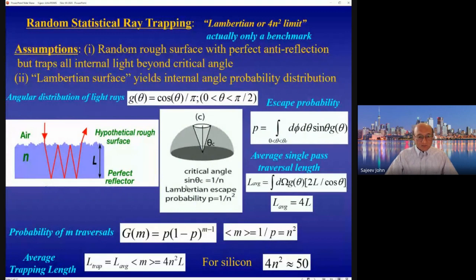So you could ask, what is the probability that light that enters the structure by this Lambertian rough surface would end up escaping from the structure? Well, if you have a material with a refractive index of n, you know from high school that the critical angle of refraction is given by the sine of that angle being 1 over the refractive index. So light would have to lie within this small cone in order to be able to escape. And you can calculate what that escape probability is, given the probability distribution of deflections. It's a simple integral over this region subtended by the cone multiplied by the distribution function, and that works out to a probability of simply 1 over n squared. So that's the probability of escape.